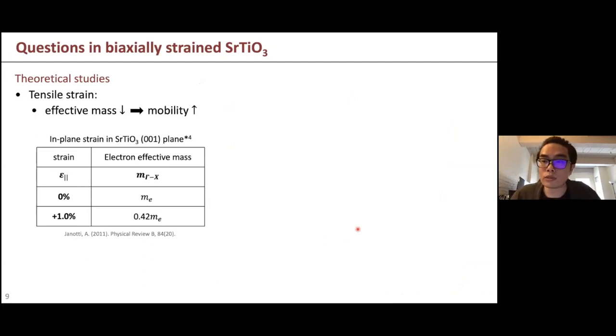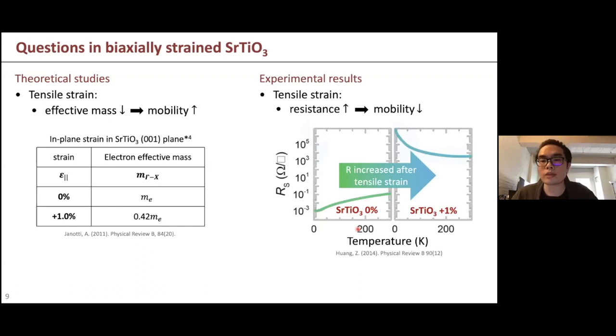In another experiment, they grew the film epitaxially and then created the strain. When they stretched the strontium titanate film, they actually found a resistance increase, and that's due to a decrease of mobility. So there's a very clear contradiction between these two studies. So which one is right? I believe that's actually not the correct question to ask, because they might both be correct.